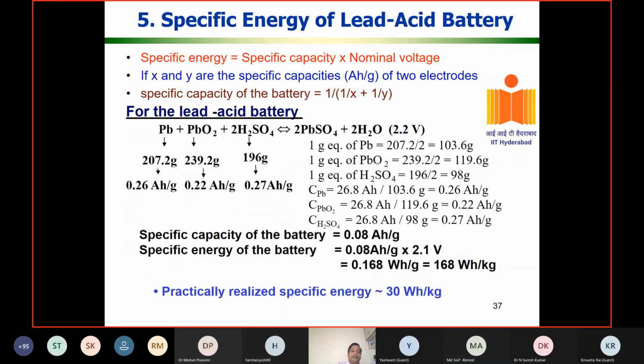Already I told you about this slide. Because lead is heavy, versus lithium, which is 6.9 gram per mole. You use aluminum foil and copper foil, which are very thin and lightweight. You use 20 micron or 15 micron aluminum foil, that's what I showed you, or 12 micron copper foil. Even now 8 micron is used. Very thin current collectors are enough for the lithium-ion cell. Whereas we cannot use them in the sulfuric acid environment, so we have to use lead grid. Lead is heavy, and I told you lead weight is 207 gram per mole, whereas lead oxide is 239 gram per mole. It's very, very heavy.